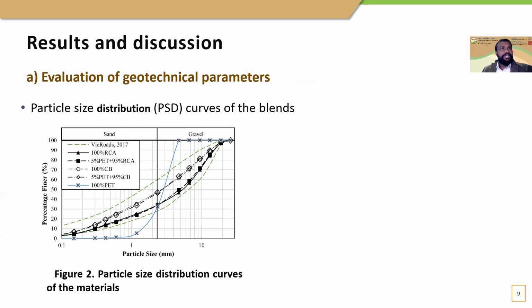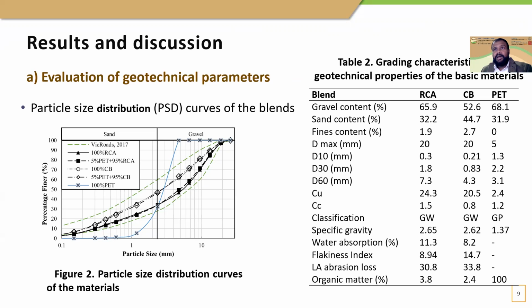Moving on to the results and discussion. First of all, the particle size distribution. The 3 control blends and the mixes of PET and CB blends were used for the basic characterization test. According to this figure 2, CB blends contain a higher percentage of finer particles than RCA. Adding 5% PET had a negligible effect on the PSD curves or grading characteristics of the PET and CB blends.